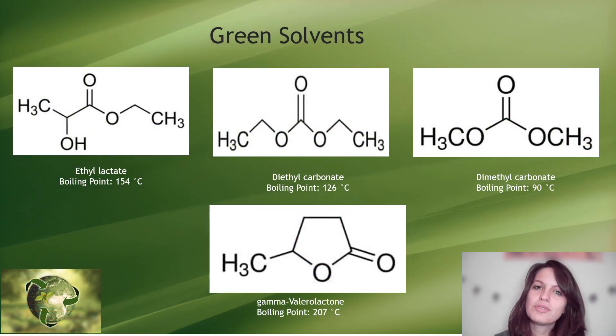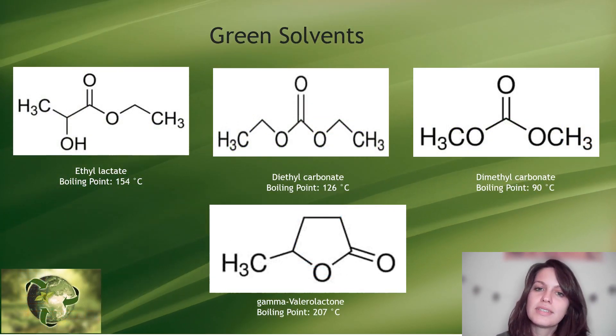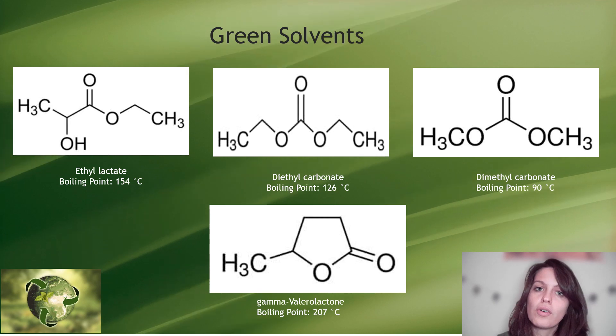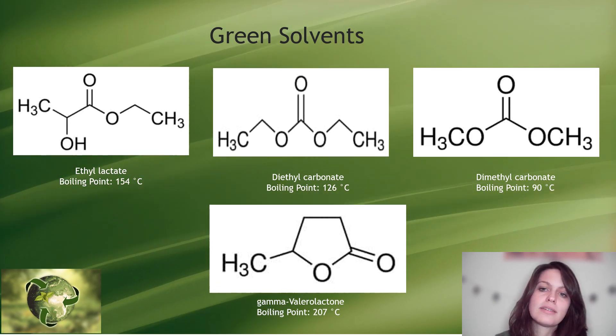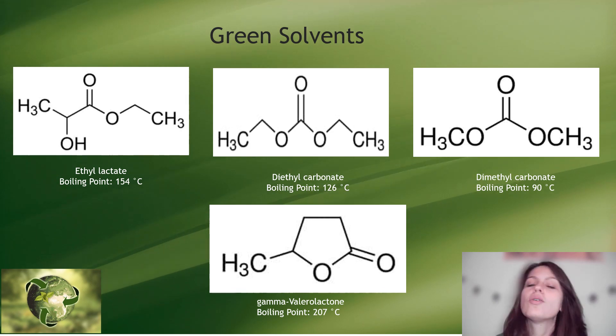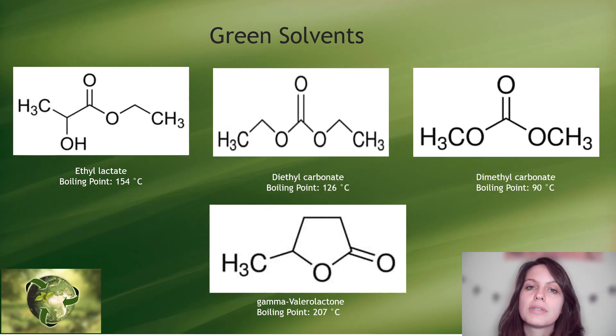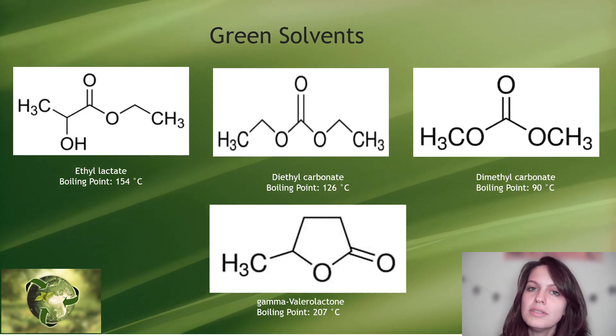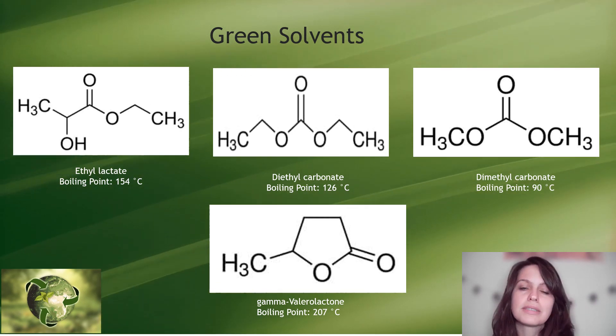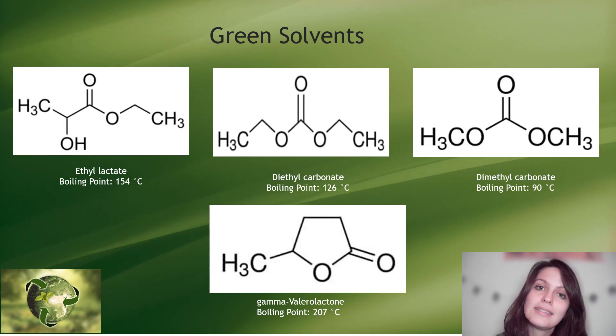After producing these mats, I saturate them with green solvents, which could be: gamma-valerolactone, which is derived from lignocellulosic biomass; or ethyl lactate, obtained by esterification of bio-lactic acid by fermentation of starch; or diethyl carbonate, obtainable from renewable sources and biodegradable; or dimethyl carbonate, which is not bio-based but green and biodegrades readily in the atmosphere.